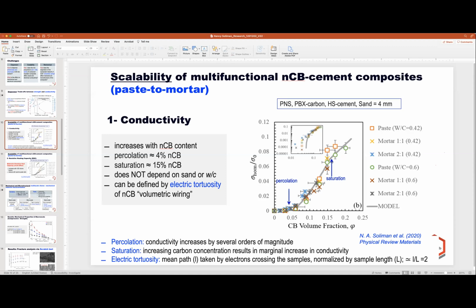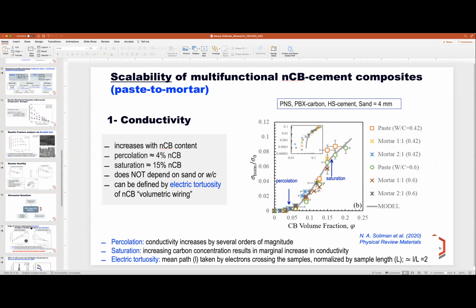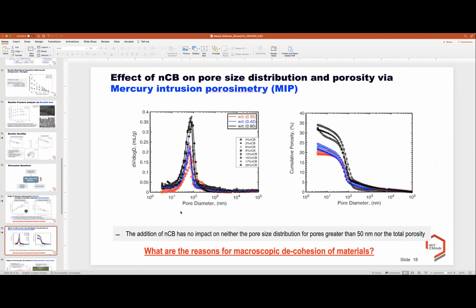On your slide 18, have you been mentioning that you don't have any effect on the porosity distribution? Yeah, I think nanocarbon black doesn't have an effect on the porosity for each family. For example, for water cement ratio 0.6, we don't see any significant impact in the reduction of porosity. So the porosity is from 30 to 34, which confirms that the reduction or the de-cohesion in the matrix comes from nanoscale. I see. Interesting. Thanks a lot. Thank you so much. Great.